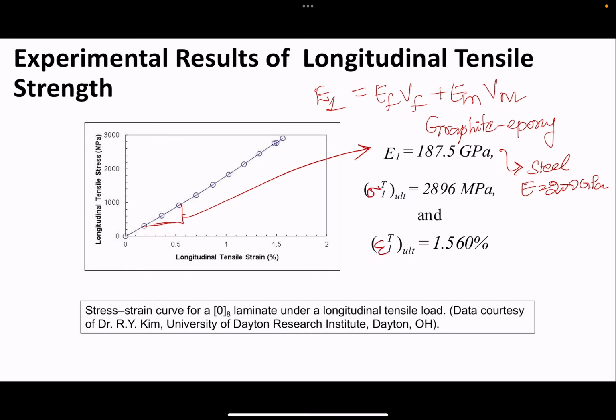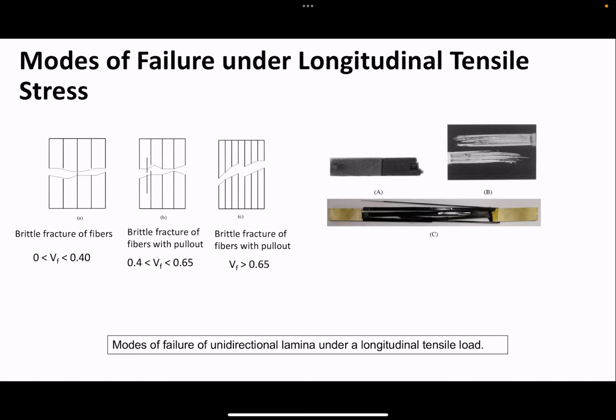So here there are 3 possible failure modes. Why do we study failure modes? Because it tells us what to look out for, it tells us how to design better, and just by observing the world around us, you get a lot of information. So here the failure mode depends on the fiber volume fraction. If you have fibers less than 40%, then you have brittle fracture, break. If you have this very common fiber volume fraction which we look for, which is between 40% and 65%, again you have brittle fracture of fibers, but there's pull out as well.